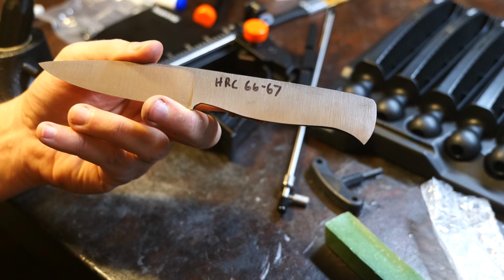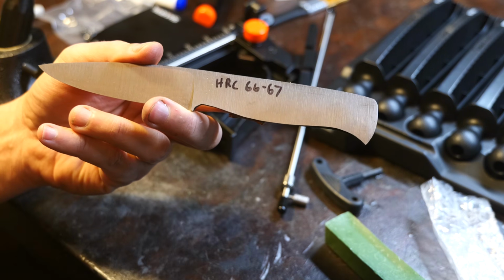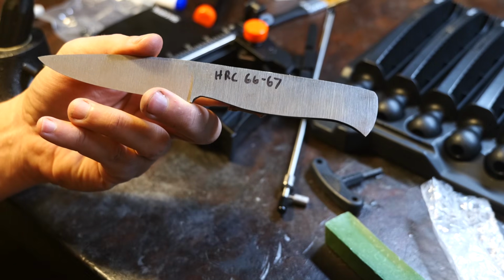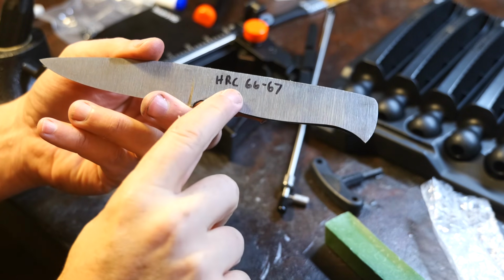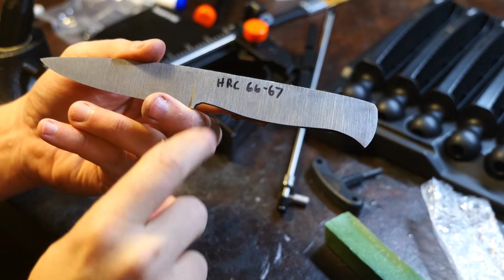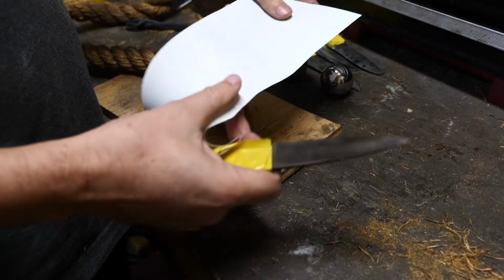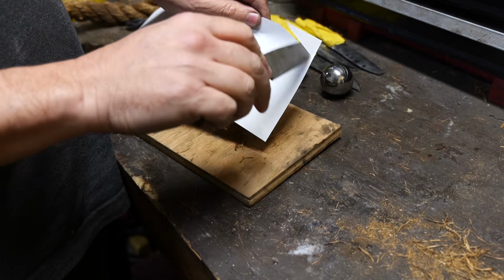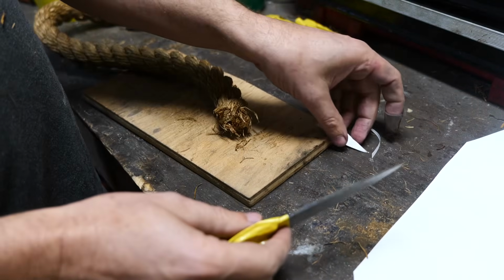Let's check it out. So after a quench from 1490 degrees Fahrenheit, we're getting HRC readings much closer to advertised here. There was 66 and 67 readings here. Once again, we tempered this down to 63, 64 HRC. That was at 315 degrees Fahrenheit.